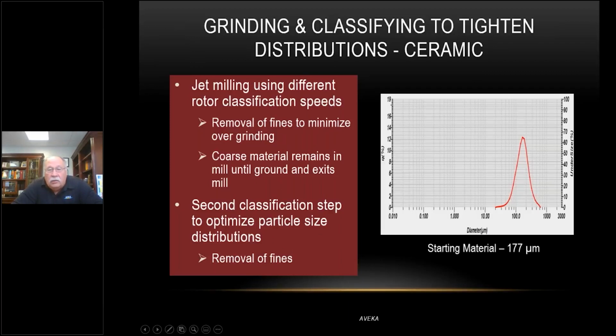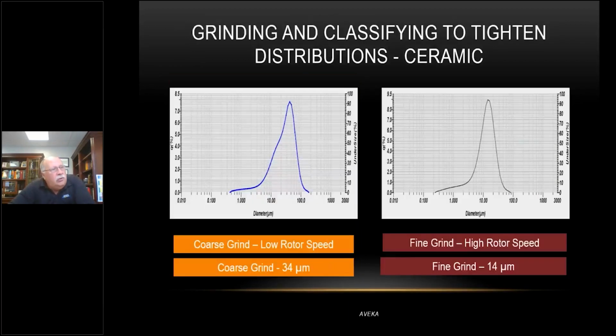So let's just take a look at what happens when we do grinding with a low rotor speed. And the low rotor speed is that classification system at the top of the jet mill. In this particular case, we took that 177 micron average particle size down to 34 microns, and we got a distribution that looks like this on the left side of the screen. Now, the interesting part about this is you notice that this is a fairly broad distribution, and for abrasives, that's not a good situation. You want a tight distribution.